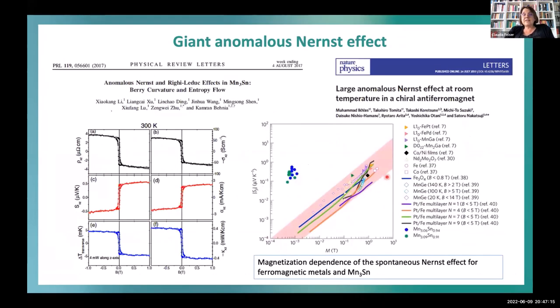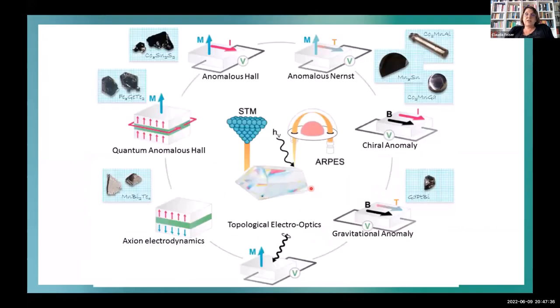Also here, we have a giant anomalous Hall effect, and we see a giant anomalous Nernst and even Righi-Leduc effect. And it's a strong deviation from the Nagaosa results. It's a strong deviation from what you expect from conventional antiferromagnets.